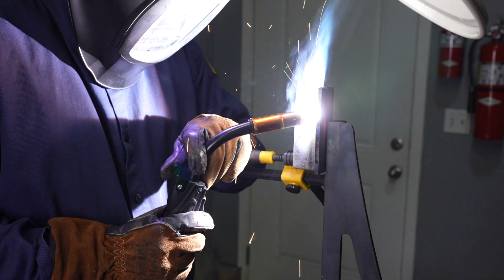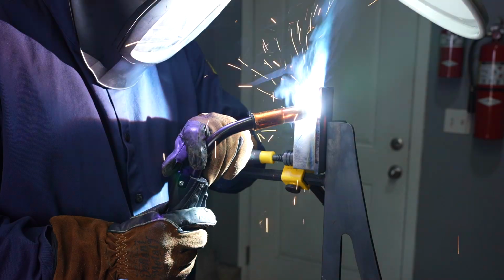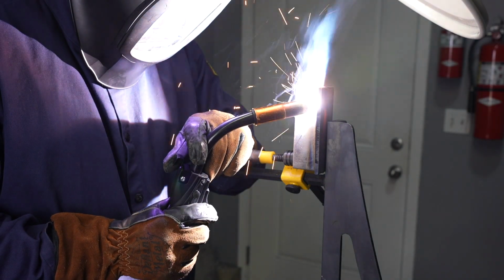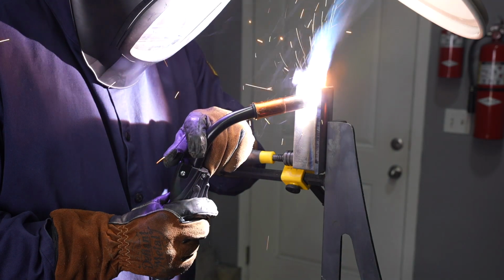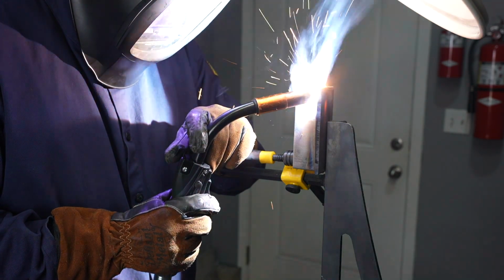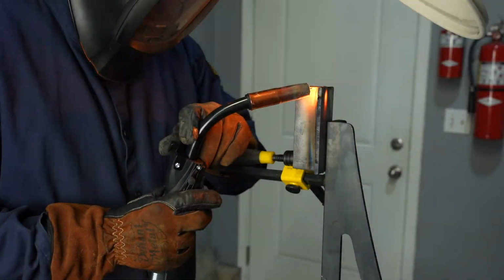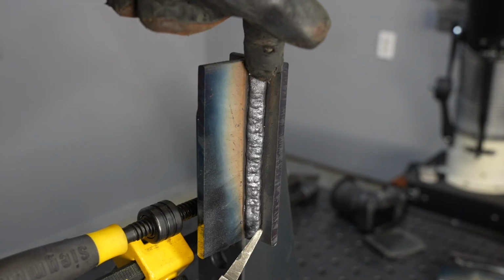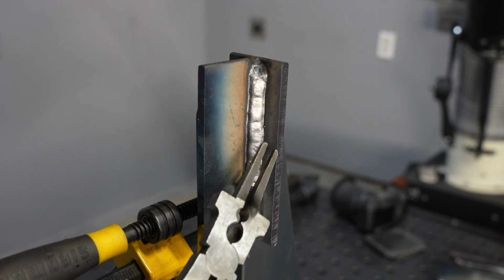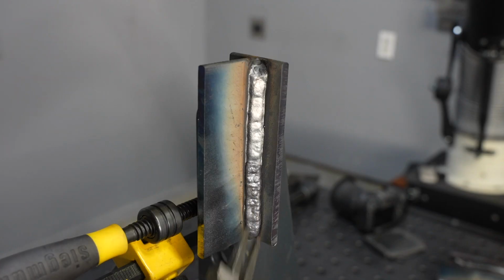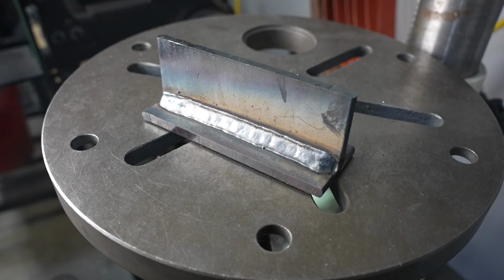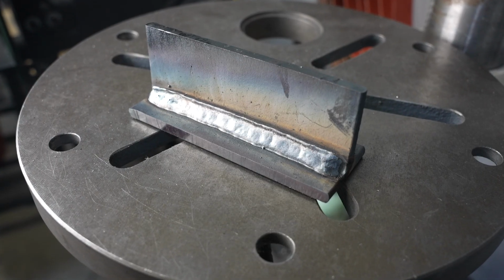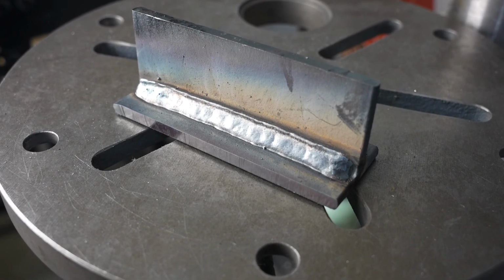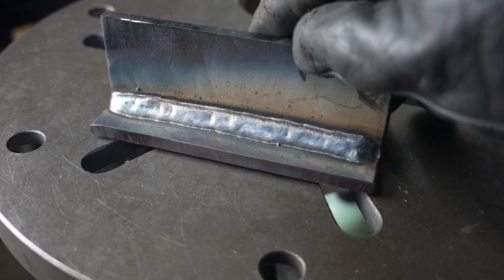Now, the important thing here is to watch your angles. I like to be heading in there about 45 degrees, but use just a very slight push angle when I'm going uphill with this wire, and you can just have confidence in the process that that slag is going to hold it in place, but it is pretty sensitive. Any little variation in your movement, you'll see you can end up with some little wiggles and wobbles. But for a vertical weld running a straight stringer on wire feed, that's really pretty good in my opinion. I'm an engineer nerd talking about it, but people who run it all day, every day, you can get pretty smooth.